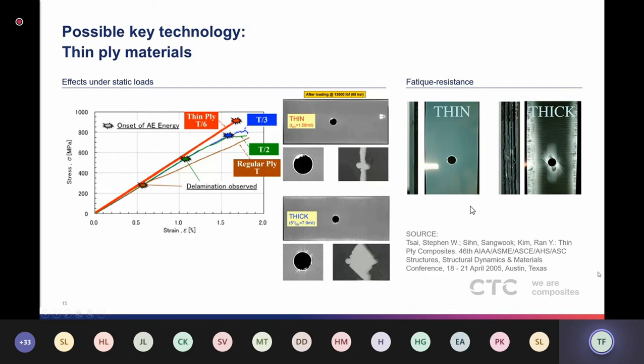The same occurs also for fatigue: no fatigue-induced cracks visible in the thin ply structure, but a lot of cracks in the thick ply structure. So we think that this is a key technology, and it's also been shown in the past that this helps with the microcrack problem. It can be used in laminates where thick plies are combined with thin plies to get this effect, because of course layup times are increased if you decrease the thickness of the plies.